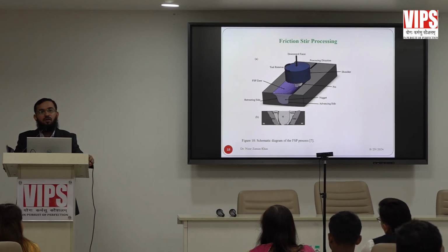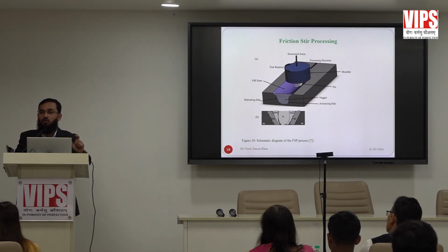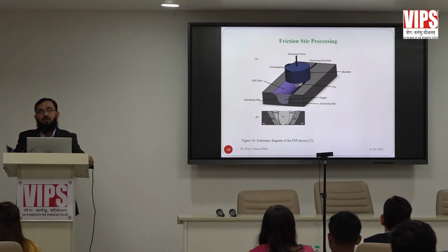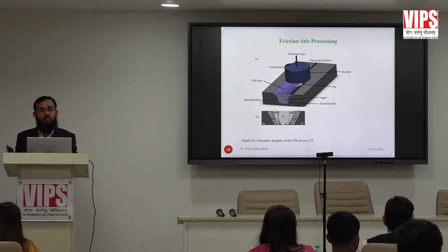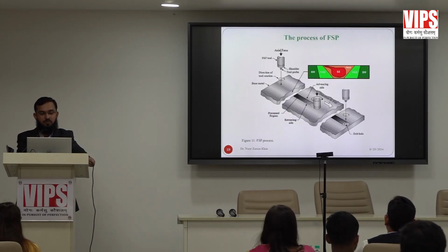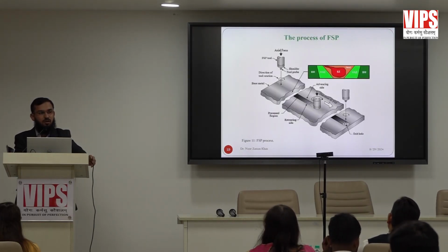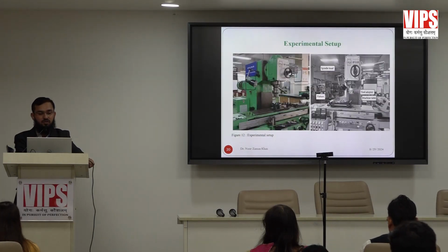It is very difficult to join these alloys, so that's why they were using rivets, and rivets have their own weight. The target is how to reduce the weight, and if we use rivets, they carry their own weight. So after 1991, the rivets were replaced by friction stir welding, and now in the Boeing Dreamliner 787, around 70% of welding is done by the friction stir welding process. Now this is friction stir processing, a solid state processing method. It uses a non-consumable tool for performing the severe plastic deformation.